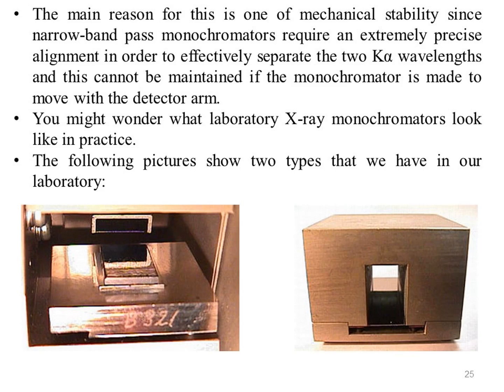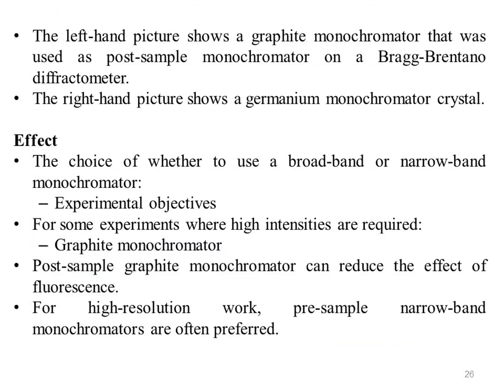You might wonder what laboratory X-ray monochromators look like in practice. The following picture shows two types that we have in our laboratory. These are different types of monochromator. The left hand picture shows a graphite monochromator that was used as a post-sample monochromator on a Bragg-Brentano diffractometer. The flat graphite crystal is stuck onto the surface of the metal plate. The right hand picture shows a germanium monochromator crystal. It is cut exceedingly thin, less than 0.5 millimeter, so that it can be gently bent by clamping it between the two curved metal surfaces of the monochromator housing.